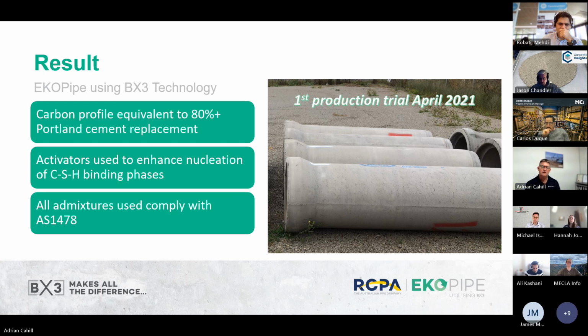So the results that we get is a carbon profile equivalent to a replacement of more than 80% of the Portland cement. We do use some activators to help that initial nucleation and development of the CSH binding phases. We still have CSH binding phases, for the cement chemist in the room. We're not creating anything unusual from a cement concrete perspective. All the admixtures that we use have been tested and comply with the relevant Australian standard. That's just a photo of first production we did in 2021.